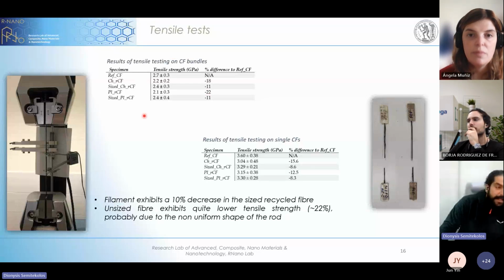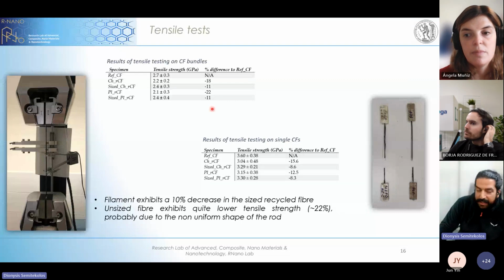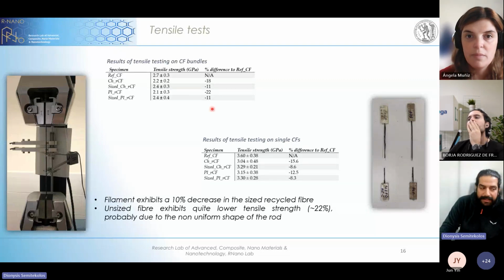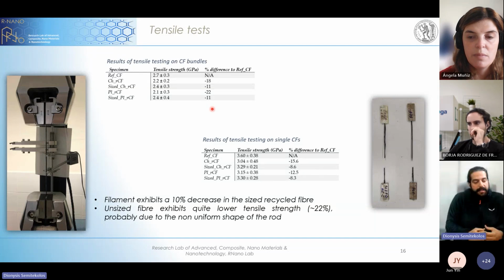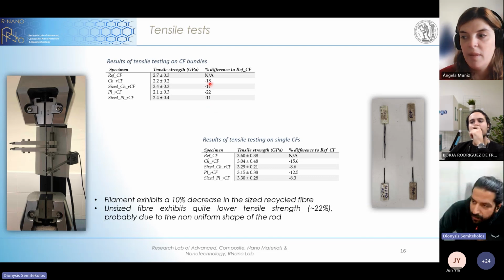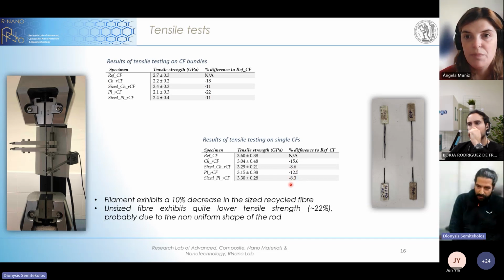Okay. And then we did the sizing with a pilot scale sizing line, and this completely changed the picture due to the fact that the rod became more uniform, and the fibers, due to the tension that we also apply during the sizing, acquire the required alignment parallel to the axis of loading. So this way we see that in the end we have approximately 10% decrease on the sized recycled fibers, which actually is a result that is consistent with the previous speaker. So this gives us extra motivation that we're doing good work.